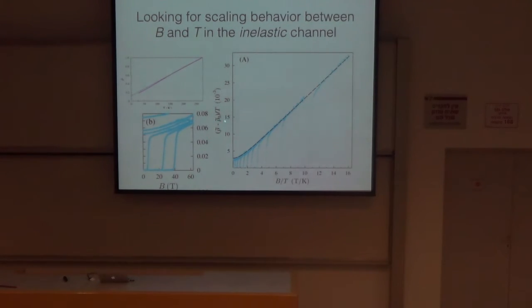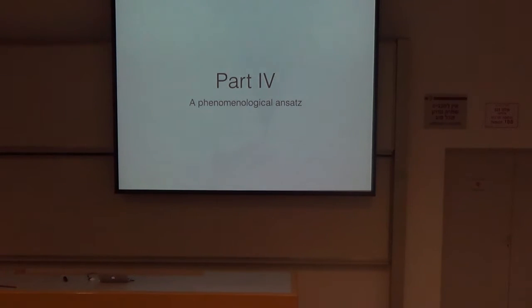So this rho minus rho naught is only what I would call the inelastic part of the resistivity, the temperature and field-dependent part, and that's what you normalize to temperature. And you plot that as a function of B over T. But this is just to see that there is such a universal function. This is the last time that we will ever take any offsets. And that rho naught is taken at zero field and zero temperature. Okay. So there seemed to be a functional form, and that was already extremely interesting.